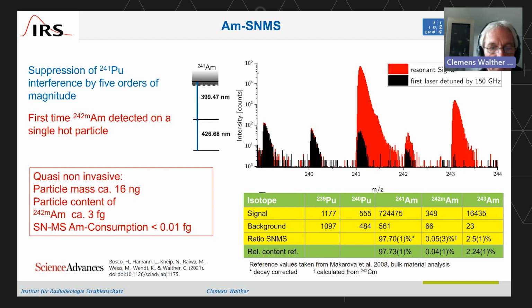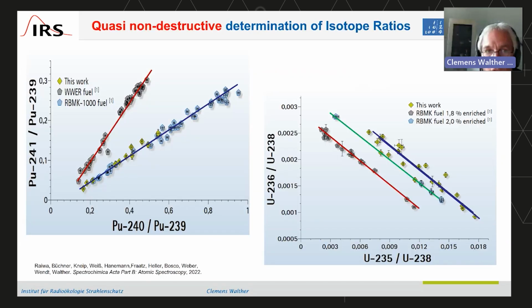That is amazing what you can do with this technique, because I told you that it's hardly invasive, meaning the particle mass is only 16 nanogram and the particle content of the americium is circa 3 femtogram, and the SNMS does not use up the particle. So even after hours or days of measurements, the particle is still there. You consume only about 10 attogram of the material to get this kind of spectra and unequivocally detect the 242m. Now we have the information on the uranium isotopes, the plutonium isotopes, the americium isotopes, and that can also be done for fission products like strontium.